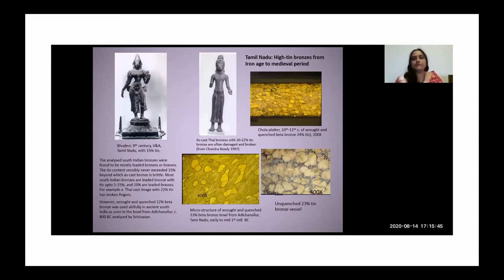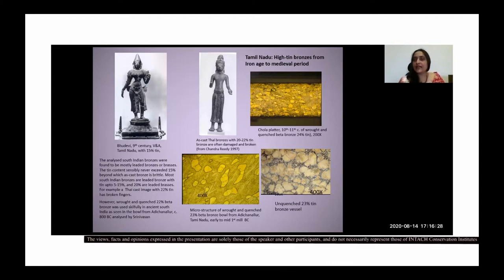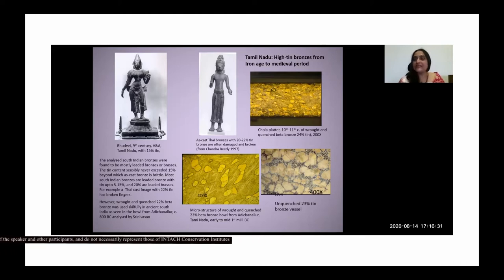Now, this image that you're looking at, the Bhudevi of the 9th century from the Victoria and Albert Museum, which I had analyzed, I put that in just to point out that that image has 15% tin. So the tin content doesn't exceed the alpha solid solution very much, so all the parts are intact and so on. But take a look at the image next to it, which is an as-cast Thai bronze, which had about 20% tin. And this was analyzed and discussed by Chandra Reedy in her article on Thai bronzes. And here you see that the hand is actually broken off because the addition of so much tin made the bronze brittle in the as-cast state.